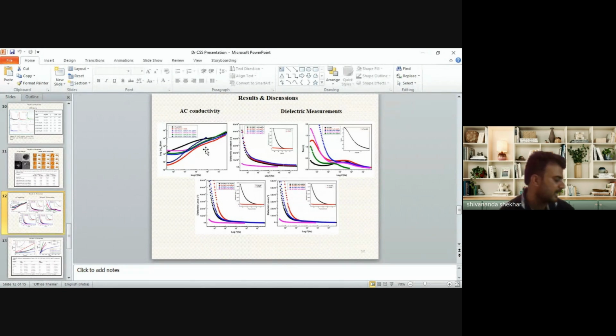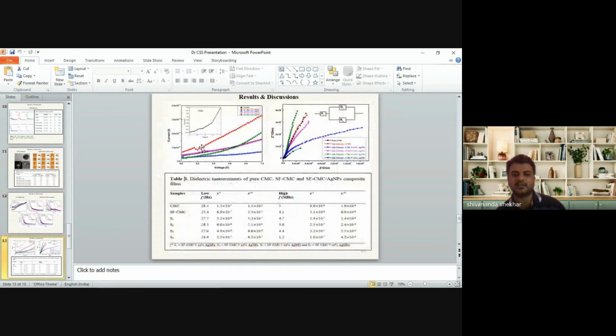The AC conductivity value increases from 4 × 10^-4 Siemens per meter to 8 × 10^-4 Siemens per centimeter. As the concentration of silver nanoparticles increases in the matrix, the conductivity of the composites also increases. We have also calculated the DC conductivity as well as the Nyquist plot, and we have tabulated the dielectric measurements of the pure sample and its composites. Here the dielectric constant, real part and imaginary part, are tabulated.